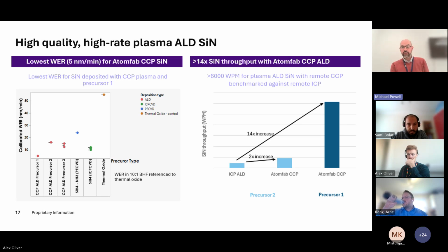The quality of the material is shown here on the left-hand graph, where we're doing a wet etch rate in buffered HF. So we've got a 10-to-1 buffered HF, and we reference that to a thermal oxide wafer to allow us to understand how quickly we are etching through the material. The lower the etch rate, the higher the quality, the higher the density. And you can see with our highest rate process, we actually have our lowest etch rate. So we've got an etch rate of about 4 nanometers a minute for that film.